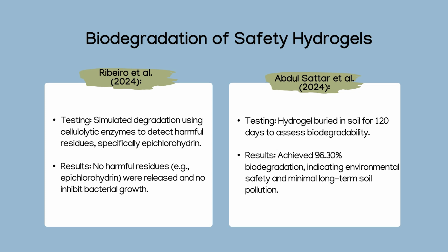What about the biodegradation of these hydrogels? Ribeiro et al. in 2024 tested the biodegradability of the hydrogel. He stimulated degradation using cellulolytic enzymes to detect harmful residues, especially epichlorohydrin. The results found that no harmful residues were released and there was no inhibition of bacterial growth.